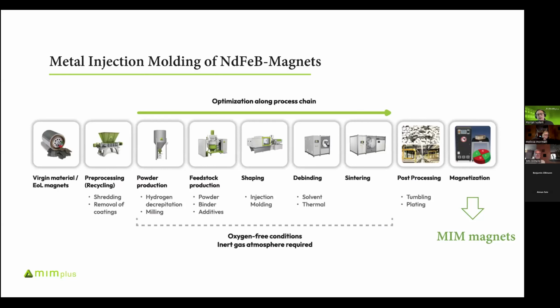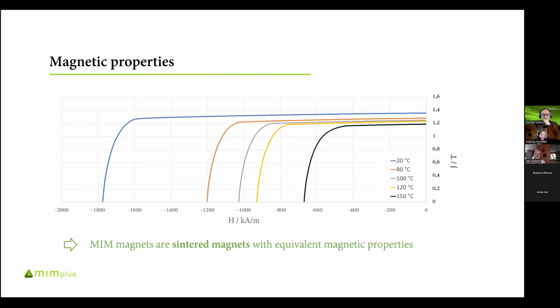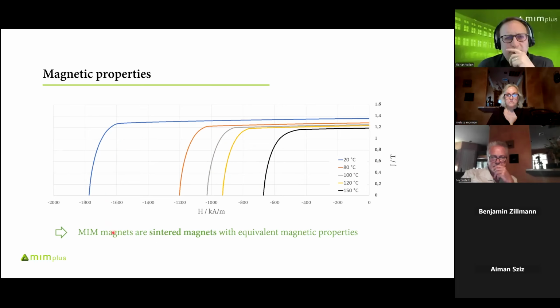Okay, now our magnet is sintered. We can do some post-processing and the magnetization, and now we have our MIM magnet. And now it's of course interesting, what are the properties? Here I have a demagnetization curve of a MIM magnet. The blue line is at room temperature, and you see the remanence, in this case I think it's 1.36 Teslas, and a coercivity of nearly 1,800 kiloamperes per meter. So this would be a grade of about N45SH.